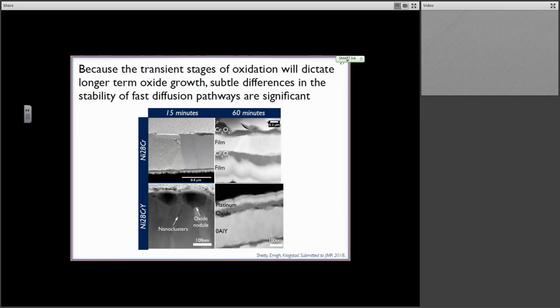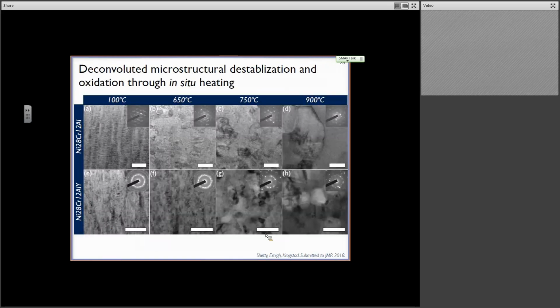Now, what we can see here is we go back and we put the oxidation back in. So the yttrium, what I didn't show you is in this particular case, the bottom one where we have this evolution, we again see these yttrium nanoclusters, except now they're distributed all the way through the thin film. There's not this denuded zone in the center because we don't have the driving force for oxidation.